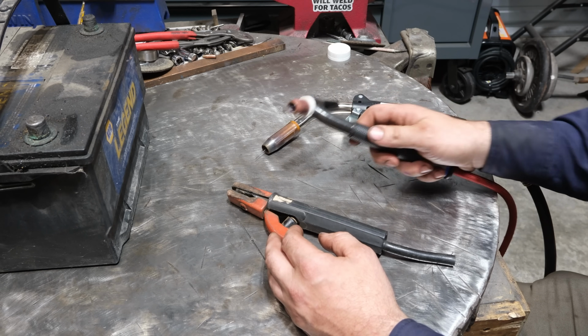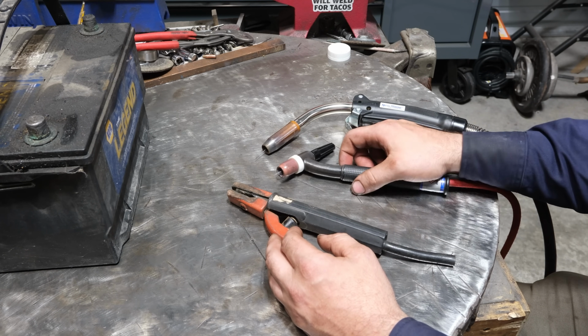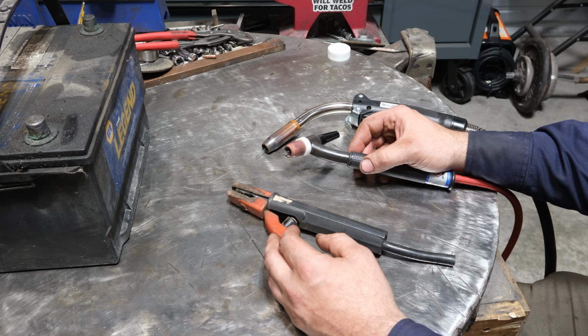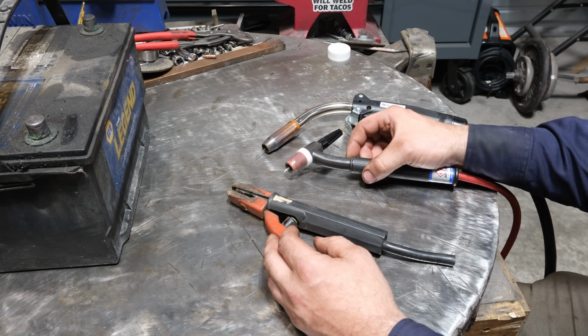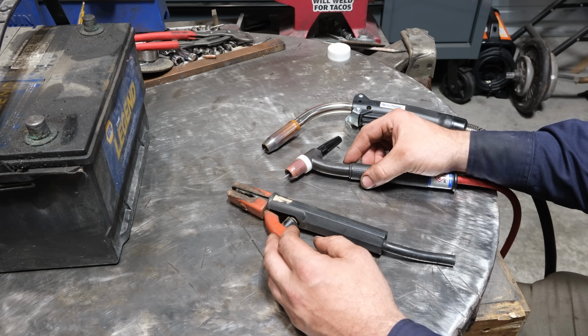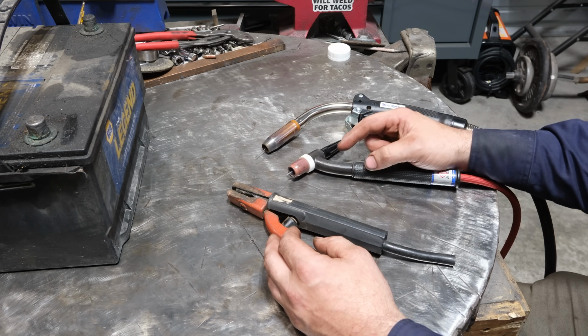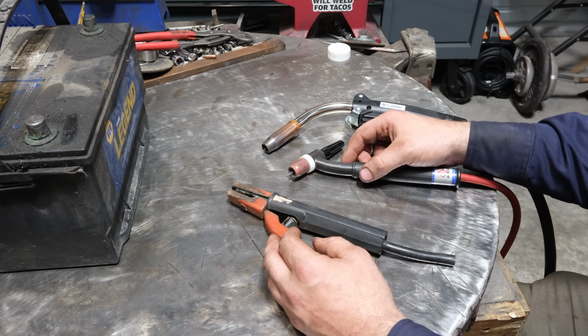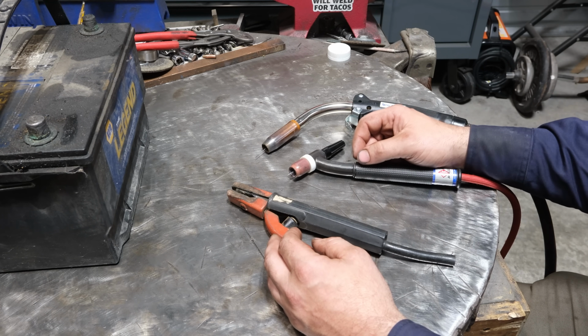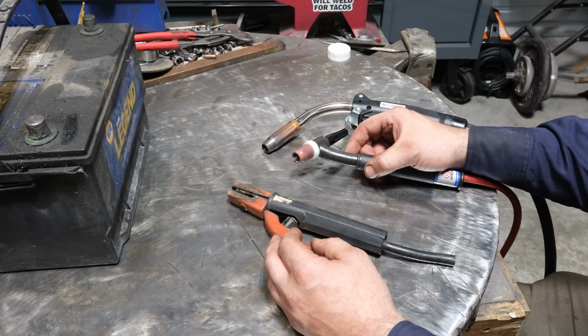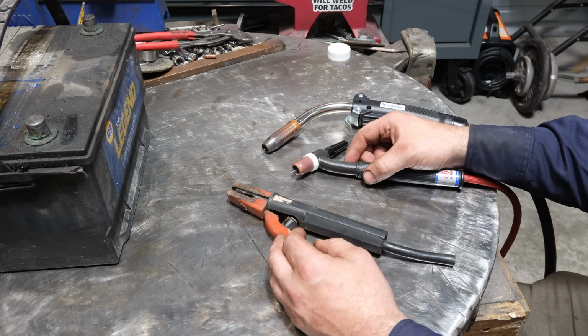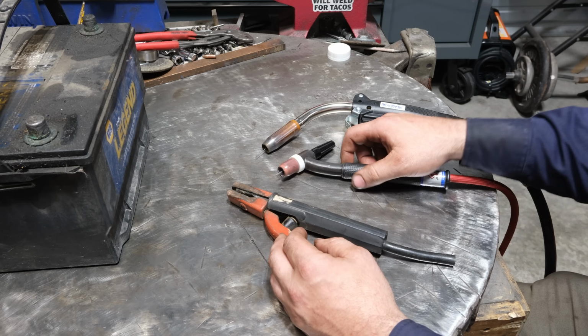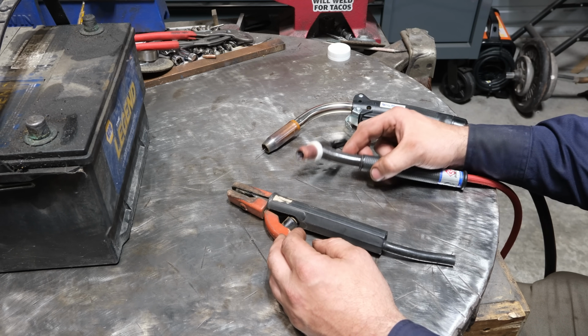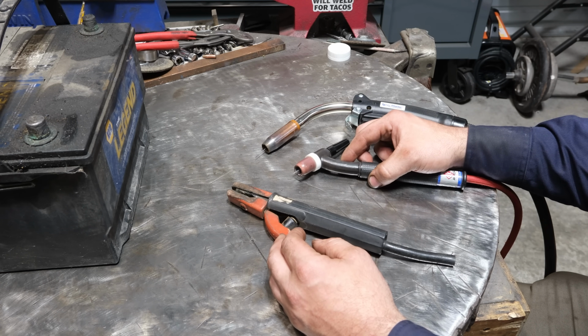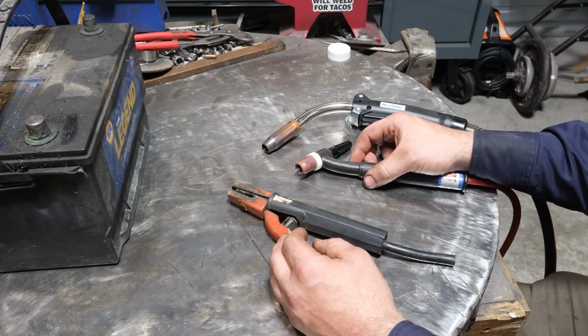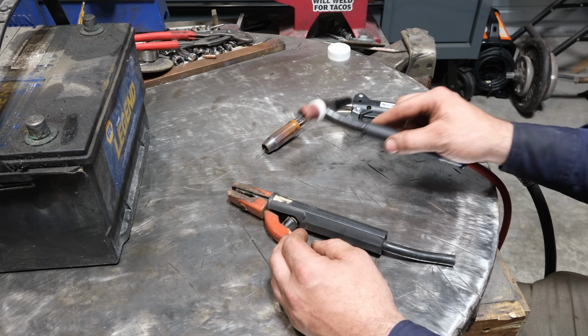Now with TIG, you can run DCEP as well. The results are a little bit less fun. It's going to involve grinding your tungsten. But when you strike an arc and run a weld, or at least attempt to do a weld, that tungsten can't handle the heat that those electrons are imparting by striking the tungsten, and you're going to end up melting and balling up that tungsten. Which, by the way, if you do a lot of aluminum welding, it wouldn't hurt to ball your tungsten with a mini ball on AC, because it will help stabilize the arc, I find, at higher amperages. So you can do that.